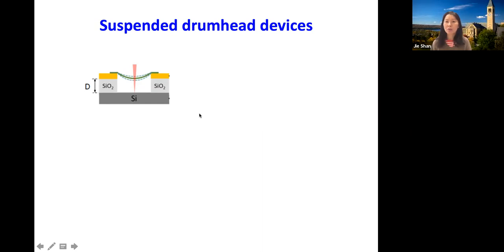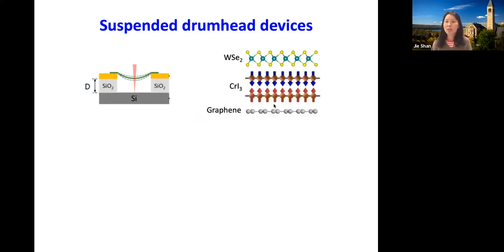So this membrane, of course, the main constituent is the chromium iodide layers. In this case, I'm showing 2 layers. And one not very nice property of this particular material is that it's very air sensitive, so we need to protect it. So we wrap it between 2 different materials. One is few-layer graphene sheet, usually 1 layer or 2 layers. And graphene is also conducting, so it serves the purpose of electrodes as well. And then on top, we put in a monolayer of semiconductor, tungsten selenide. And this serves not just as a protection layer, it's also a strain sensor.